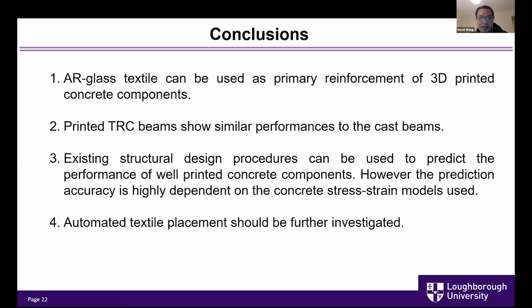I will go to the final part of this presentation. The first conclusion is that AR glass textile has been demonstrated to be usable as a primary reinforcement for 3D printed concrete components. If the printing quality is well controlled, the printed TRC beams show very similar performance to the cast concrete beams. For the analytical part, if the concrete quality is well controlled, existing structural design procedures can be used to predict the performance of printed concrete components.